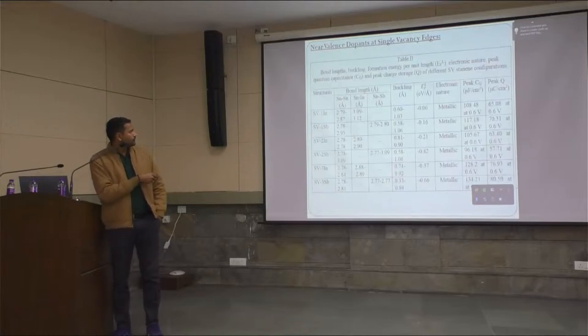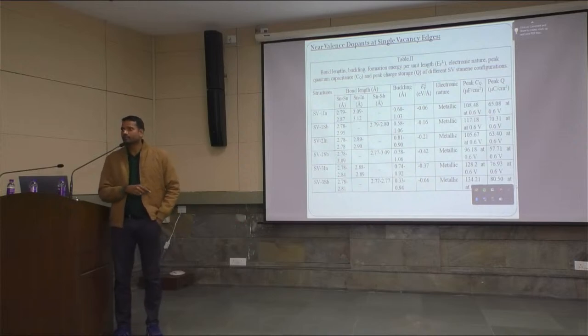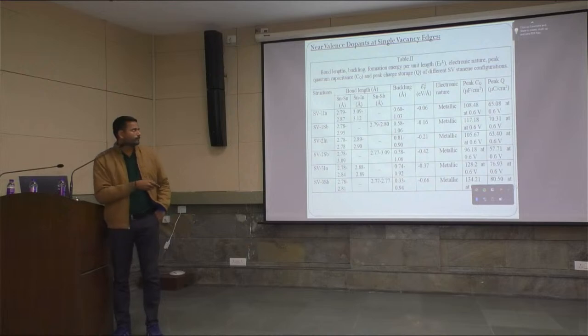And so this is the data. We can see here, when we do one indium and one antimony, the antimony is offering better thermodynamic stability than indium. Similarly, when we do two indium and two antimony, the two antimony is offering better thermodynamic stability. Similarly, with three antimony, we are getting better thermodynamic stability. And antimony is also offering better quantum capacitance in comparison to indium. So we can say in stanene, antimony is a better dopant in comparison to indium.